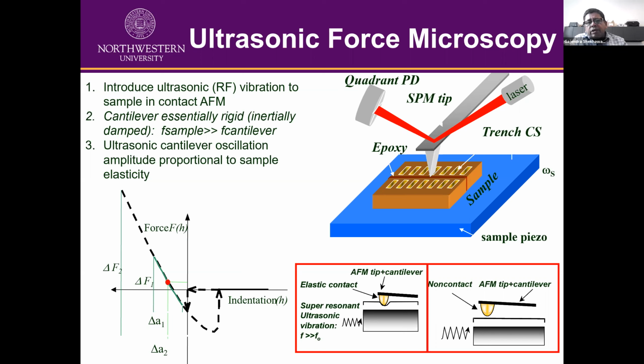So this technique came, ultrasonic force microscopy, where we oscillate the sample at a pretty high frequency. So you can create an out of plane vibration of the sample, and that indents the probe to a high contact force with elastic contact. So basically you can compress that part. And then that technique allows you to measure the mechanical properties. Through force distance curves, you can extract the mechanical properties of the layers below that. How deep we can go, we haven't tried that much, but a few layers below the surface, you can do it.